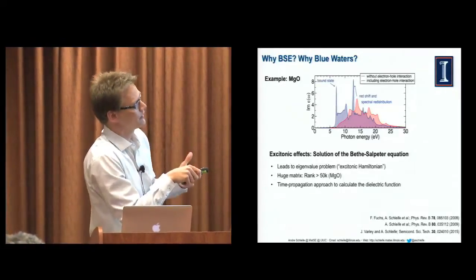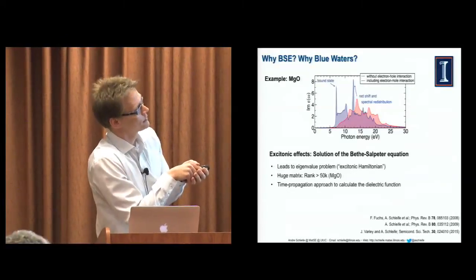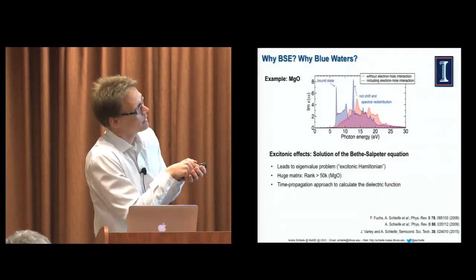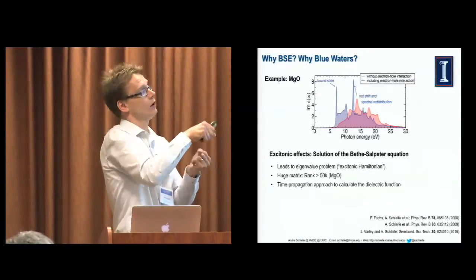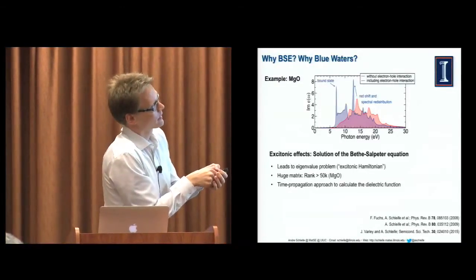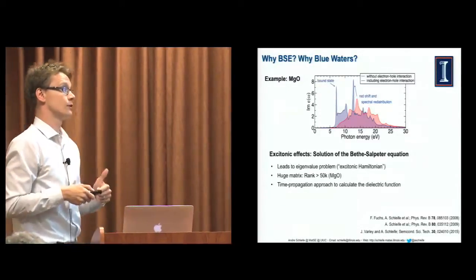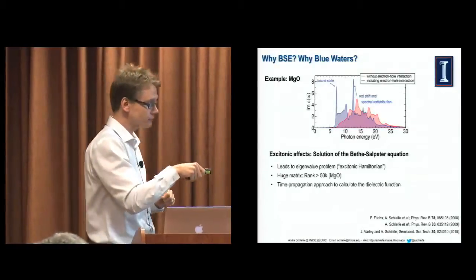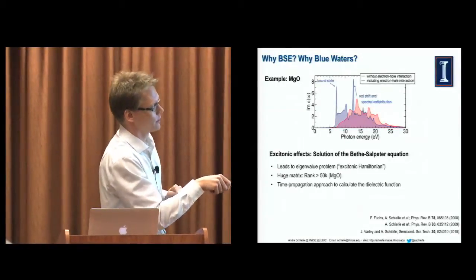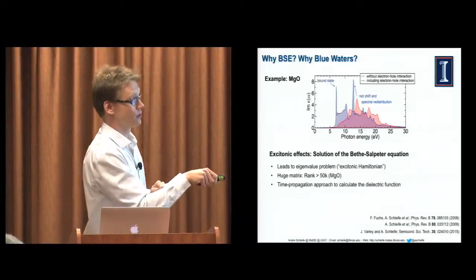We get especially two features that are kind of typical. One is this bound state here, right at the band gap. This is so-called bound electron-hole pair. And then we get for higher energy peaks this kind of redshift. That is something that people observe for many semiconductors. What it means in practice is we calculate a large matrix, so-called excitonic Hamiltonian.